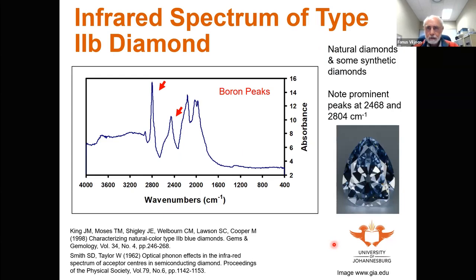When we do encounter blue diamonds, as you can see here, a nice polished stone of a fancy blue, you can see again that we have no nitrogen peaks present in the nitrogen region, but what we do see here is vibrational bonds which correspond to boron. And I would imagine that these are carbon-boron vibrational bonds. You can still see the carbon-carbon bonds over here, so we're clearly dealing with diamond, but these peaks over here are very typical of boron-containing diamonds with their marked blue color.